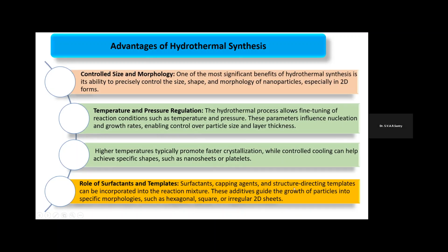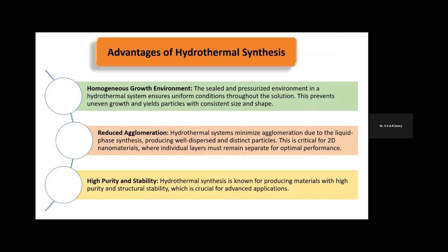Surfactants, capping agents, and structure directing templates can be incorporated into the reaction mixture initially, before adding it to the autoclave. These additives can guide the growth of the nanoparticles into specific morphologies like hexagonal or square or irregular two-dimensional sheets, etc. Further, we can also have a homogeneous growth environment inside the autoclave using the hydrothermal synthesis method. The sealed and pressurized environment ensures uniform conditions throughout the solution, which also prevents uneven growth, and the yield of the particles is with consistent shape and size.